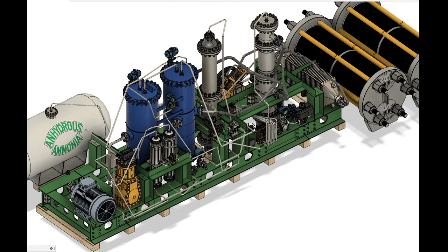Using 1 centimeter of insulation wrapped around the vessel, the heat flux for a 10 kg per hour, or 87 ton per year reactor, would only amount to 120 watts, corresponding to 1.7% of the total hourly heat flux. For a 53 kg per hour NH3 reactor, approximately 1,400 mm tall, with a surface area of 1.3 square meters, with 10 centimeters of microporous insulation installed, would shed around 135 watts, or 135 watt-hours, corresponding to a heat loss percentage of 0.0036% of the hourly heat flux.